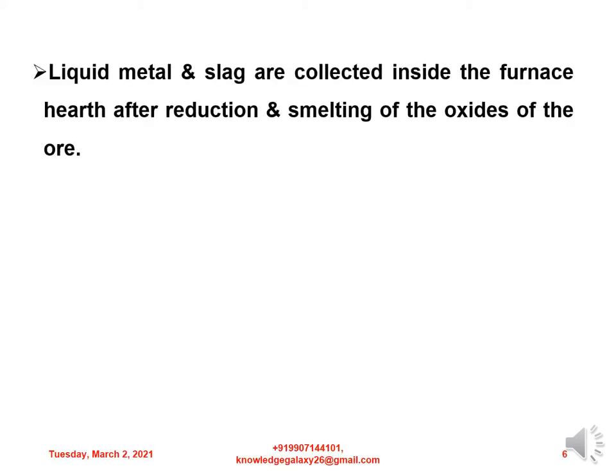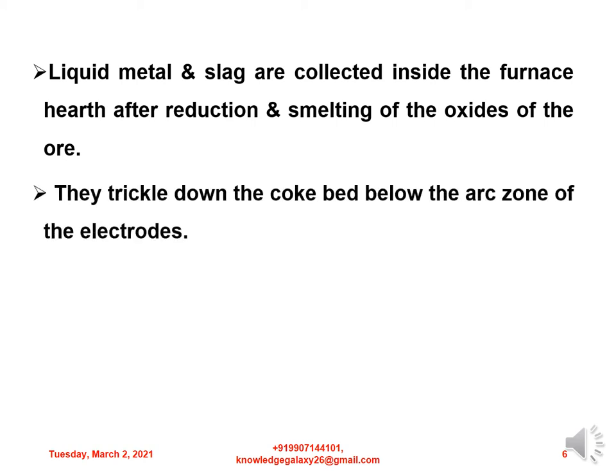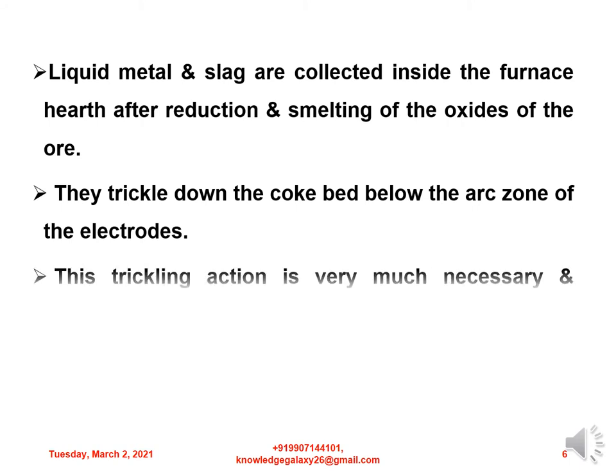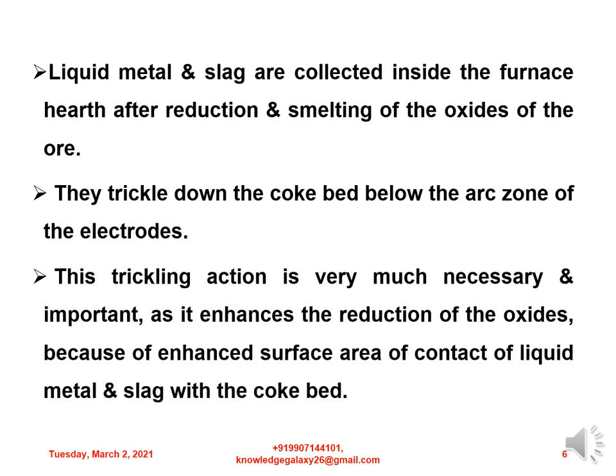Liquid metal and slag are collected inside the furnace hearth after reduction and smelting of the oxides of the ore. They trickle down the coke bed below the arc zone of the electrodes. This trickling action is necessary and important as it enhances the reduction of the oxides due to the enhanced surface area of contact of liquid metal and slag with the coke bed.